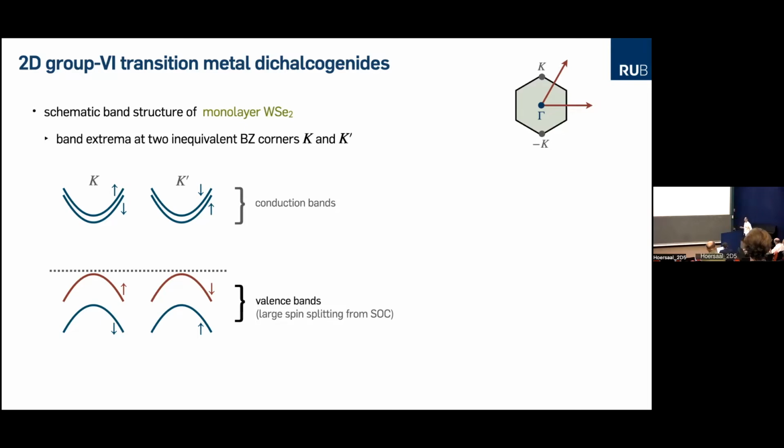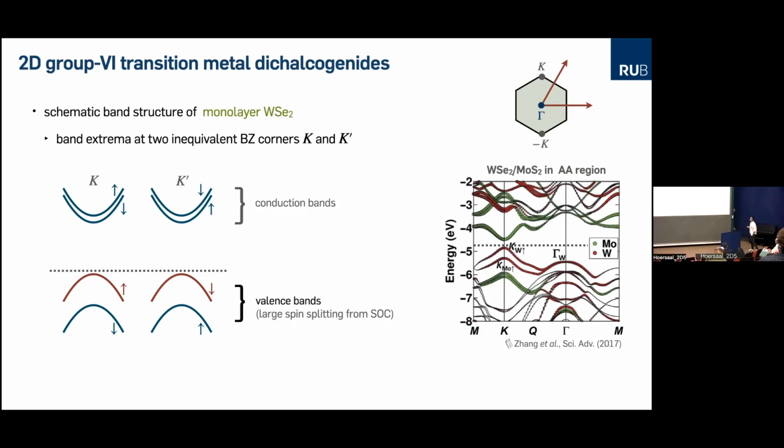And we can focus on this particular one, even if we are considering the Moiré system consisting of these two different transition metal dichalcogenides, because when you look at this a little bit closer from the ab initio calculations, you realize that the Fermi surface is really close to this valence band maximum of the tungsten diselenide, but it lies really deeply within the gap of the other material, which is shown in green, the semiconducting gap of molybdenum disulfide. So basically, when we look at the active electrons close to the Fermi level, we can basically ignore the effect of the molybdenum, but we have to take into account what it really does: it makes this Moiré pattern. So it introduces a new periodicity into the system, which we have to take into account. So we will focus on these tungsten diselenide valence states, which lie inside the molybdenum disulfide gaps.